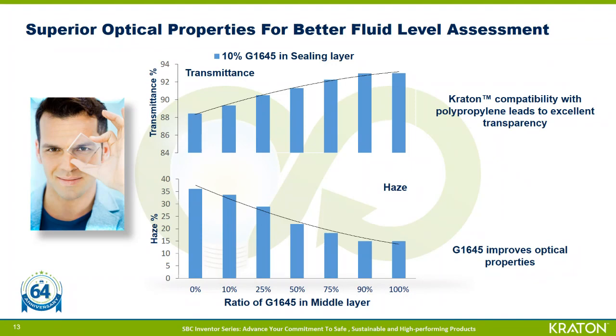Here we have further data on optical properties of the films made using G1645 and polypropylene. The polymer microstructure of G1645 allows for excellent compatibility with polypropylene, and this results in very fine dispersion in the final blend. So the data here shows that the transmittance increases systematically as the amount of G1645 in the middle layer is increased. And here we have shown you the data with 10% G1645 in the sealing layer, but it really holds for all compositions, all loading levels of G1645 in the sealing layer. We can also see the opposite trend with respect to haze, where haze decreases systematically as you increase the amount of G1645.